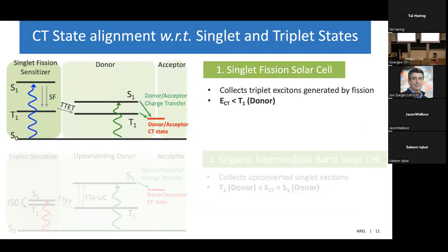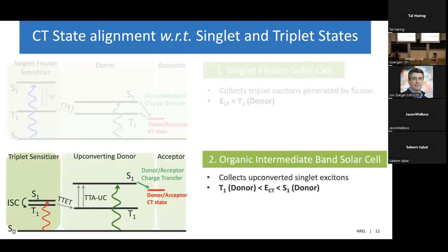So something I didn't really emphasize earlier, but is actually quite important in both of these types of solar cells, is the relative alignment of this donor-acceptor charge transfer state with respect to the singlet and triplet levels of our various constituent materials. Right, so for the singlet fission solar cell, in order to actually take advantage of the triplets that are being generated through fission, we need this donor-acceptor CT state to lie lower in energy than the triplet of our fission material. On the other hand, for this organic intermediate band solar cell, we want to restrict the photocurrent generation only to the singlets that have been produced through this upconversion process. And as a result, we want our donor acceptor CT state to lie somewhere in between the singlet and triplet states of our upconversion material.